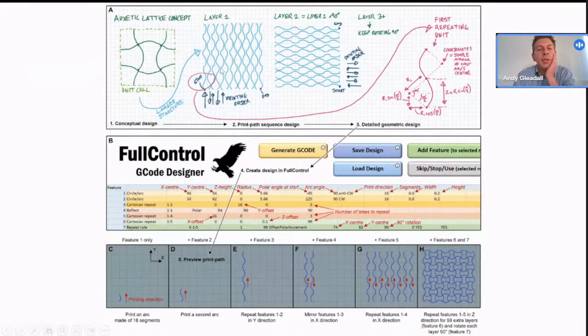The one issue with that is that these lines, the horizontal ones, are kind of colliding and printing through the vertical ones. And you do get some defects there, really microscale defects, where the filament, as you're printing towards a line, will get a bit wider. And then after the nozzle crosses the line, it takes a little bit of space for the actual extrusion to get to its full width again. So there's this kind of narrowing, and that is a mechanical defect. One way to avoid that is if you then print in the opposite direction on the next layer, then the defect will be on the other side of the line, and you'll have a bigger buildup on the same side. So you can kind of offset those defects.